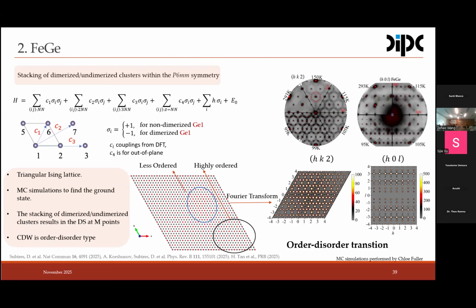Both in the HK2 plane and the H0L plane. So the message I want to convey here is that unlike ScV6Sn6, where the charge order is driven by a softening of a mode, here the charge density wave, I wouldn't call it charge density wave, I call it just a periodic lattice distortion or a structural distortion, is a canonical order-disorder transition, like it happens in the spin glasses, for instance, right?